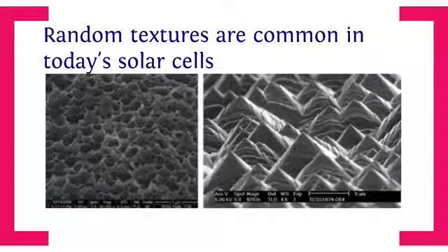But these are examples of solar cells. If you take a solar cell, open it up, the glass, you may not see it in all of them, but you put it under an electron microscope, it'll look like this. Very rough. This is either the silicon layer or something called silicon nitride, which is used for passivation, which means it tries to make the crystal structure of silicon nice and clean. So even though this looks kind of messy, the atomic structure of silicon has to be nice and clean with no dangling bonds. Dangling bonds are very bad for charge carriers, which we'll talk about when we talk about solar cells. Okay, but that's kind of what it looks like.